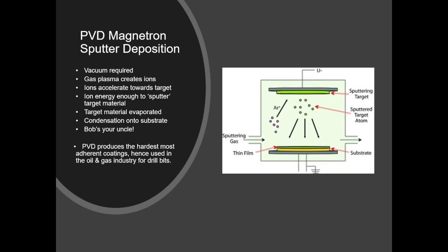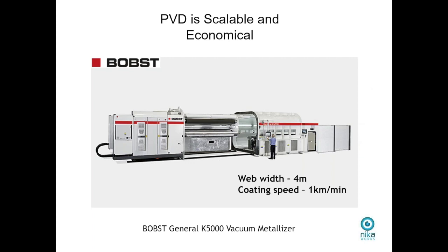And because we get such a dense, adherent, hard coating, that means that it doesn't have to be very thick. Typically, PVD coatings are about 0.5 micron. If you go to plating or other processes, you're up to tens, hundreds of microns, or even millimeters in some cases. So that's what makes PVD a little bit different.